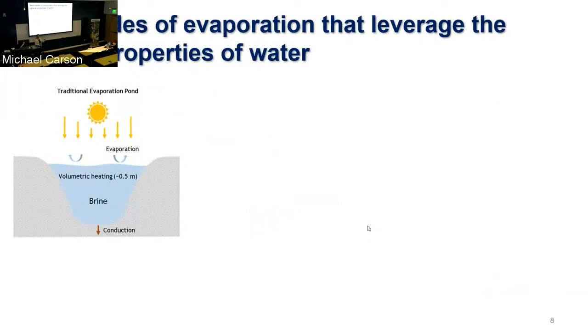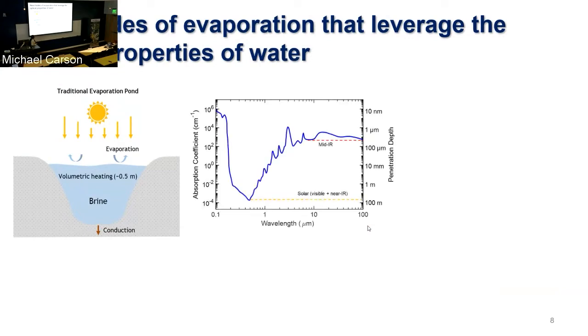So I showed you about using these porous photothermal converters in order to evaporate water. In that case, you're essentially wicking the water up to the surface. But we can also design these non-contact photothermal converters, which never really touch the surface of water, but still accomplish the same goal. So here I'm showing you that same evaporation pond. And as sunlight comes to the surface of the pond, essentially it heats up that full volume, because water is a very poor absorber of sunlight.